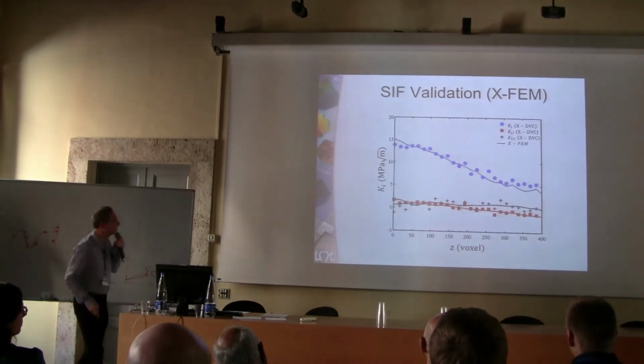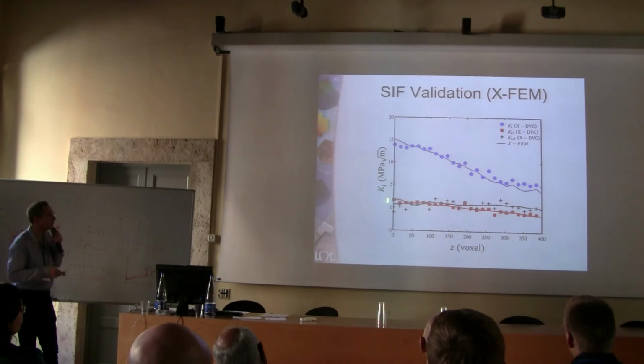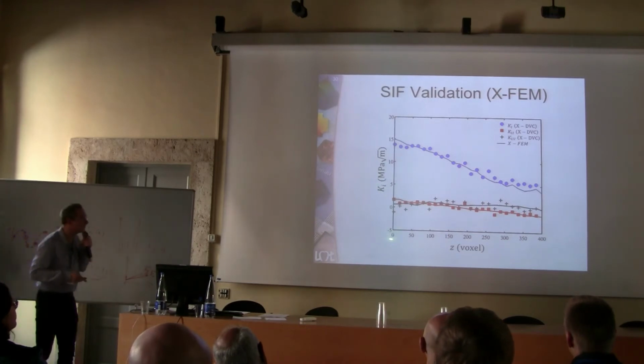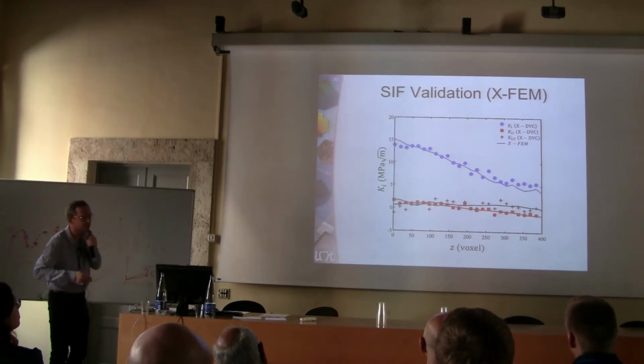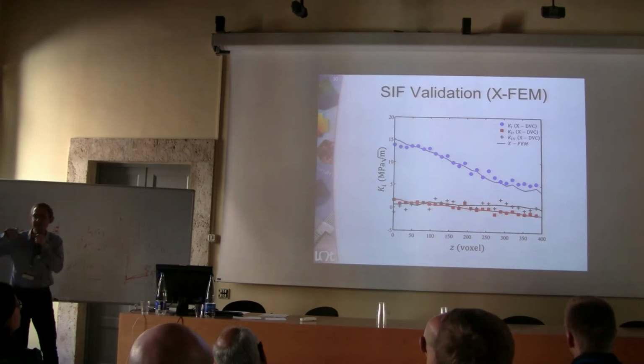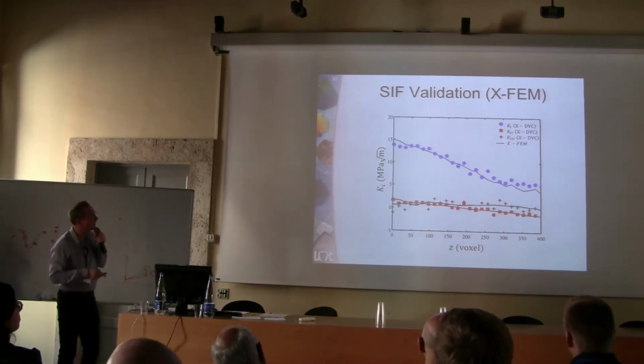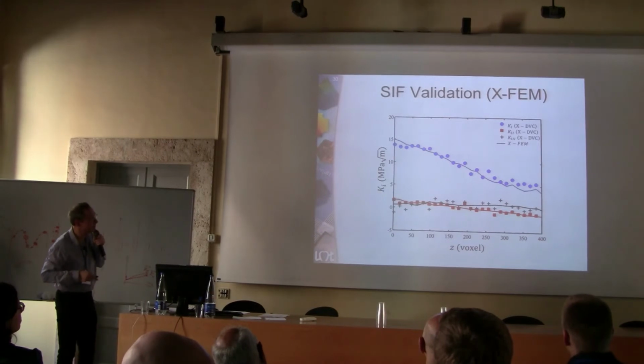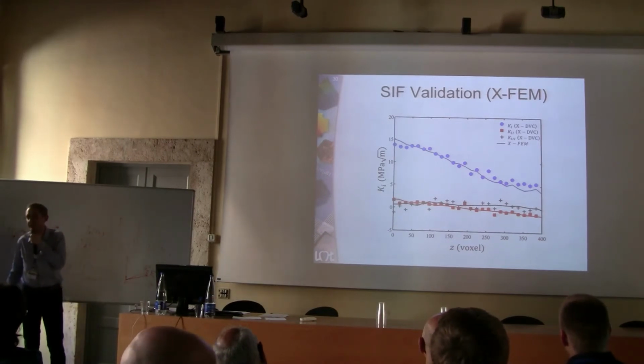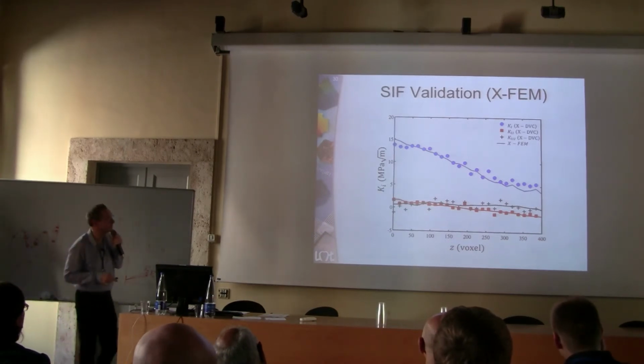In this particular case, here is the mode 1, 2, and 3 stress intensity factors along the crack front, so we are basically traveling within the material. The solid lines here show you the XFEM simulation results.